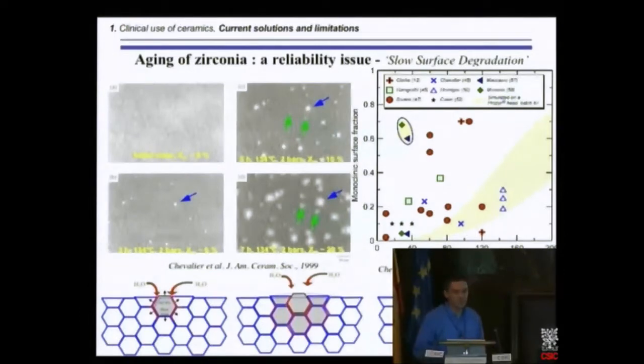And here you have a plot of different retrieval analyses from us and from other colleagues. What we see first is that there is a large scatter in the data. But anyway, for most of the prostheses, after some months or some years in vivo, there is a significant amount of degradation. We have to say that these 3 experimental data are consistent with our simulation because it was the same batch of material. We were lucky to make a retrieval analysis on the same batch. So our simulations are quite okay and in agreement with experimental data, but what is important is that there is a large scatter. For example, for this prosthesis, after only 2 years in vivo, almost all the surface is degraded. That's not acceptable, of course.